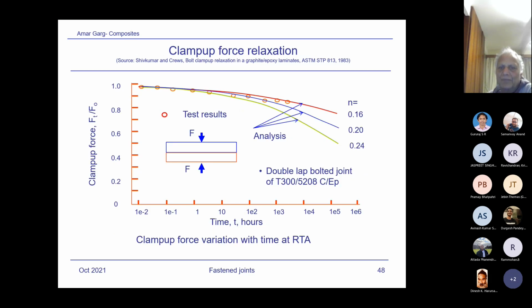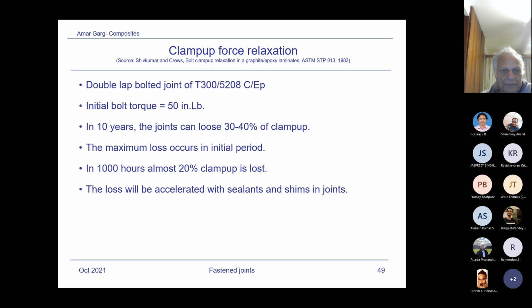Now, the result is, based on analysis, as you can see for some joint, and of course it will depend upon the thickness of the straps. But what Shiv Kumar found, that with time, the relaxation, and this is a test data, and this is analyzed data, analysis, and this is a test. So you can see, say in 1,000 hours, the relaxation in the clamp up occurs by about 20%. It's a logarithmic chart, and so you can see initially the relaxation will be more, and later on the rate of relaxation will reduce. So just a description which I have described anyway.